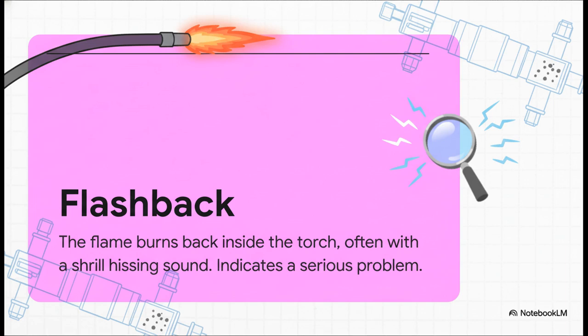Okay, we have to talk about a critical failure mode, a flashback. This is when the flame actually burns backward, up from the tip, inside the torch. It's often paired with a really distinct hissing or squealing sound. This is an extremely dangerous situation. The immediate emergency procedure is to shut off the oxygen valve on the torch first, and then shut off the acetylene valve. Oxygen first, and you do not, under any circumstances, relight that torch until you have found and fixed the root cause, whether it's a clogged tip, wrong pressures, or damaged gear.